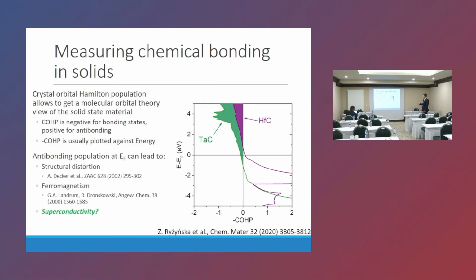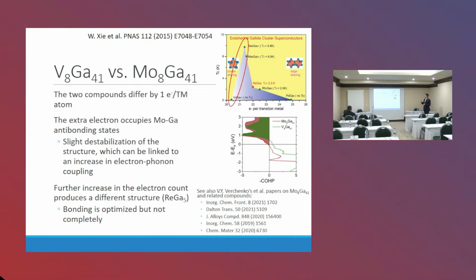So it's a figure from our paper from 2 years ago. An example of such a phenomenon is found in those two carbides. These are sodium chloride type carbides: hafnium carbide, which is non-superconducting down to like 0.01 Kelvin, and tantalum carbide, which is just one electron over, which has a Tc of 10 Kelvin or so. So we pushed additional electrons. Now the Fermi level lies in the antibonding region and it superconducts. Great. So let's get back to the